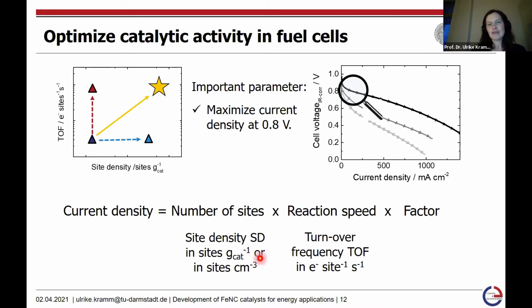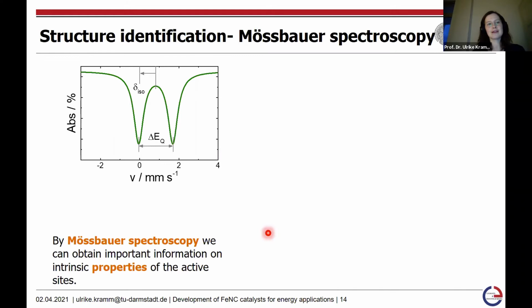But luckily, we have a lot of iron within our system in these FeNC catalyst materials. And based on that, of course, we can use Mössbauer spectroscopy for the structural identification of the catalyst. So Mössbauer spectroscopy can give you the fingerprint basically from the iron sites within the system.